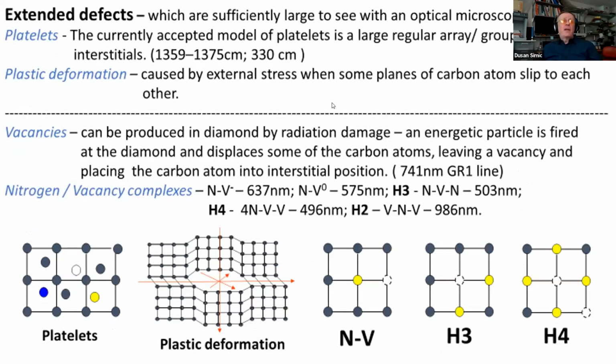And extended defects actually are much more interesting, because that's why everything with annealing started, because of these brown diamonds. Their color is caused by plastic deformation, so caused by external stress when some planes of carbon atoms slip relative to each other. And this is a defect that we are removing from the diamond structure. Also, here are some vacancies that will be automatically removed, and during all the treatments, some changes in the nitrogen and nitrogen-vacancy complexes will occur.